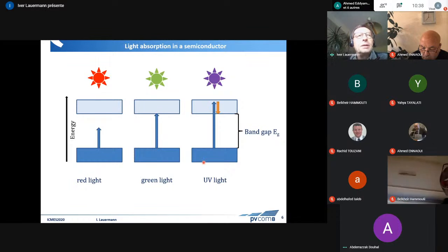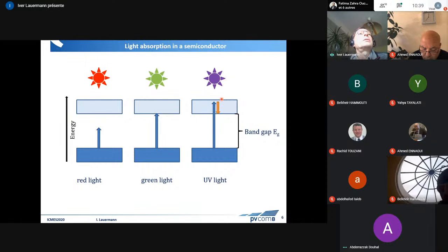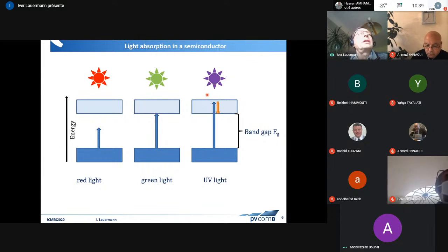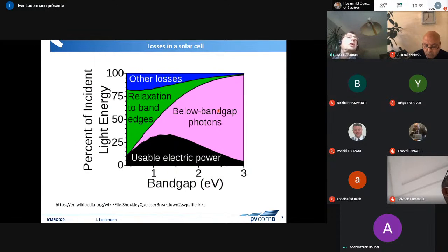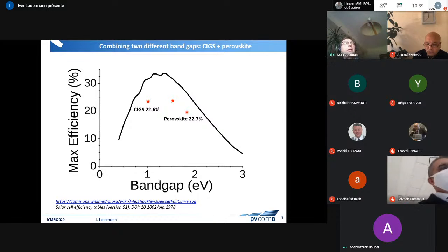If we have higher energy, we can only utilize the part that corresponds to the band gap, because carriers that get excited to a higher level very quickly lose their energy and end up here at the band gap. So the result is, if we look at this graph here, we have, depending on the band gap of the material, a certain portion of usable electric power. And you can see this is on the order of 30%. And we lose the high energy electrons by relaxation to the band edges, and we cannot even use the below band gap photons. So these are the losses if we use just a single material.